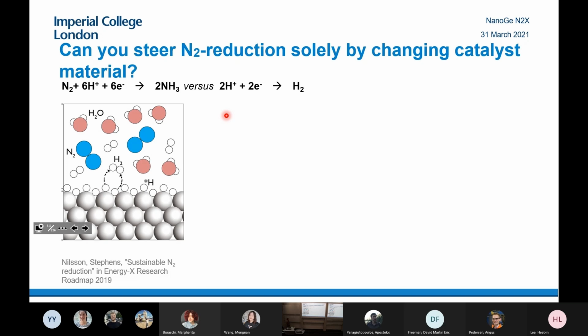So ideally what we do, and do the same as we were doing oxygen reduction, is we take a metal surface and put it into an aqueous electrolyte. This would be great if you could do that for nitrogen reduction. This is what we're very accustomed to doing. However, what tends to happen is that nitrogen is really inert, protons are really reactive. Protons will, at the reducing potential, form absorbed hydrogen, shown here, and then you end up blocking the surface, and you can't reduce nitrogen to ammonia.